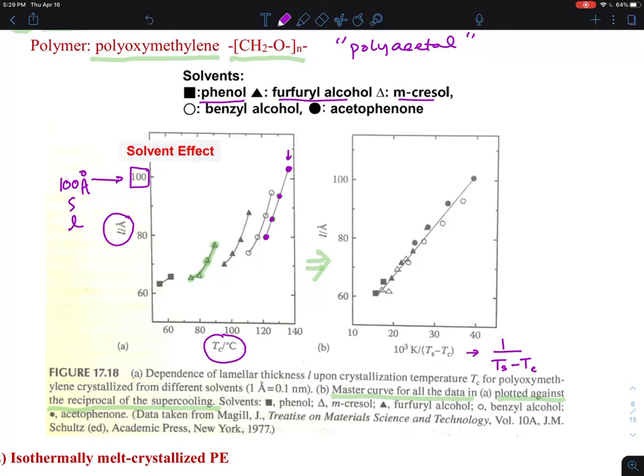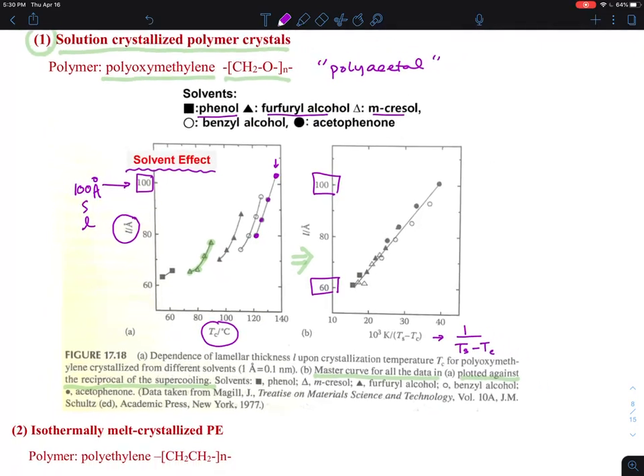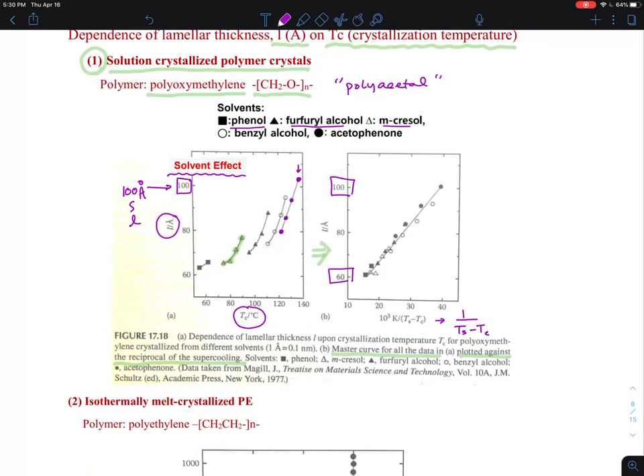They are using this temperature at different crystallization conditions to control. They find out it is a matter of different supercooling quenching depths for you to have this thickness that ranges from, let's say, 60 to 100 angstroms. So this is particularly when you have this polymer grown from the solution. Interaction from the solution certainly plays a role in growing the crystal.